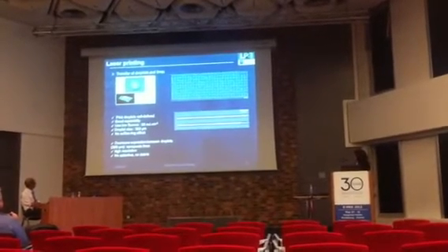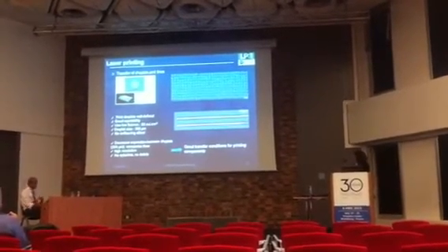If we decrease the distance between two droplets, we can print lines. In lines, we can see there are no splashes, no debris, and a very smooth profile. And if we apply this kind of transfer, we can print some components for microelectronics.